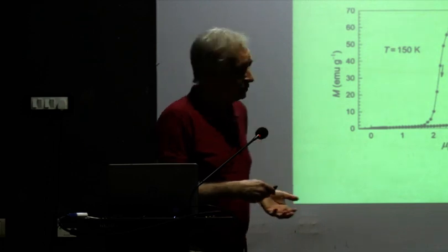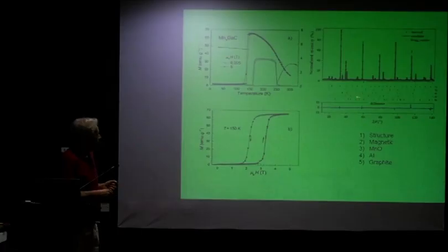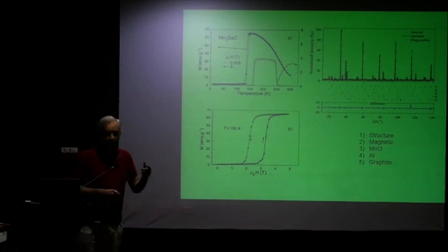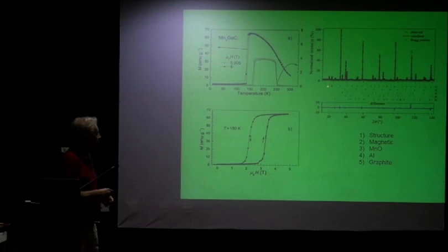That is just the standard Bragg positions, or when you're talking about neutrons, you call them nuclear Bragg positions or nuclear positions. And then you have the magnetic scattering, which you see here. So you see that this peak would not be there if you had measured this at high temperature. This is a purely magnetic peak which is coming out, this one here.